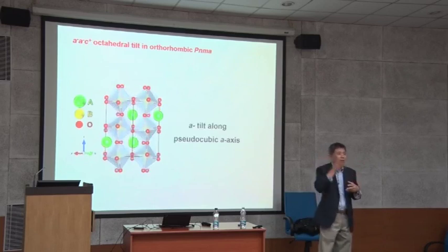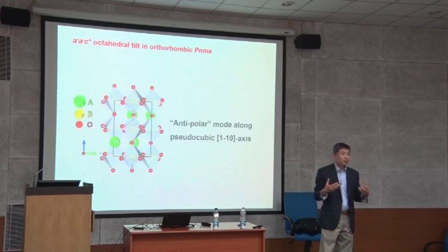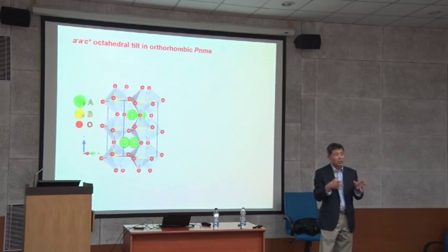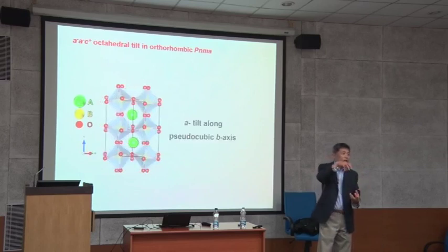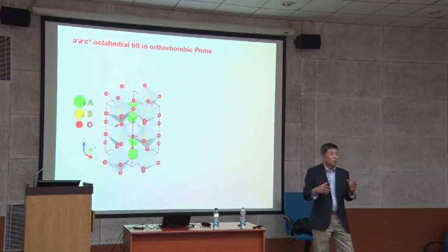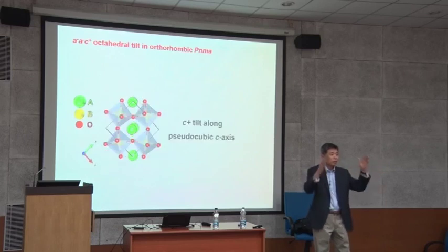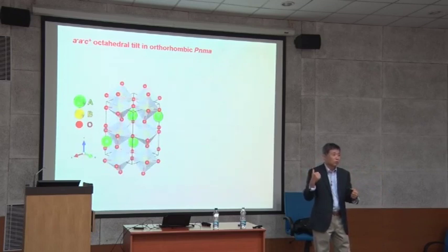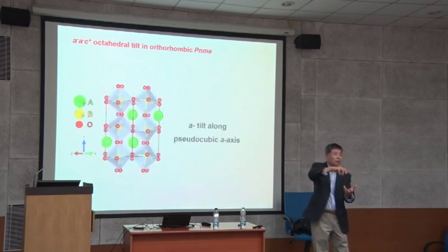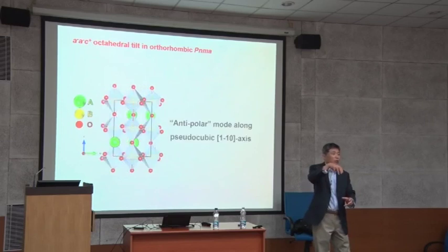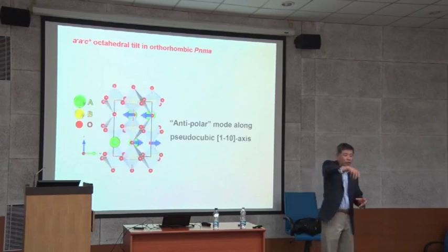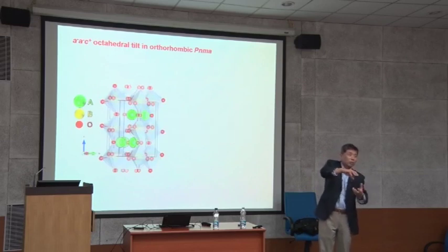So you're creating patterns like minus, minus, zero. For example, the rhombohedral phase like lanthanum aluminate has a tilt pattern of minus, minus, minus, which means all out of phase. And this orthorhombic structure is minus, minus, plus, the orthorhombic crystal structure form. You can have many notations, many structures, subgroup formation, but I talked here just about the orthorhombic structure, minus, minus, plus, which can be controlled by the substrate rotation pattern of minus, minus, minus. Because the substrate is minus, minus, minus, and the material we are growing, a polar metal, is minus, minus, plus. The plus is trying to go one way, the minus goes the other way, so we can turn it in the other direction, and that's what happened.